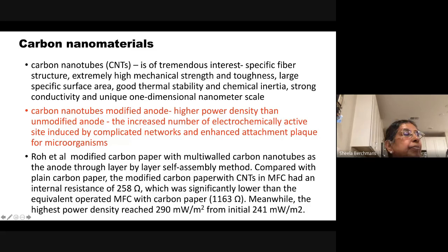There is a report in the literature about carbon paper modified with multi-walled carbon nanotubes as the anode through a layer by layer self-assembly method, compared with plain carbon paper. The modified carbon paper with CNTs in the MFC had a low internal resistance of 258 ohms, which was significantly lower than the MFC operated with carbon paper alone. With carbon paper alone, the internal resistance was 1163 ohms. In the presence of CNTs, it decreased to 258 ohms. Meanwhile, the highest power density reached 290 milliwatts per meter square from an initial 241 milliwatts per meter square.